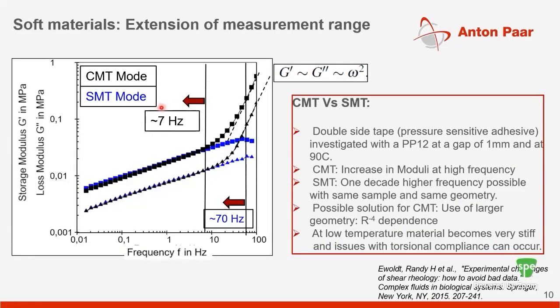The first example I want to show you is a classic pressure sensitive adhesive example. Pressure sensitive adhesives are a great example for soft materials, right? When you're characterizing moduluses, which can vary from all the way up to 1 megapascal in some cases, down to several hundreds of pascals. Typically people in this industry do a lot of frequency sweeps—they're heavily used in the PSA industry.